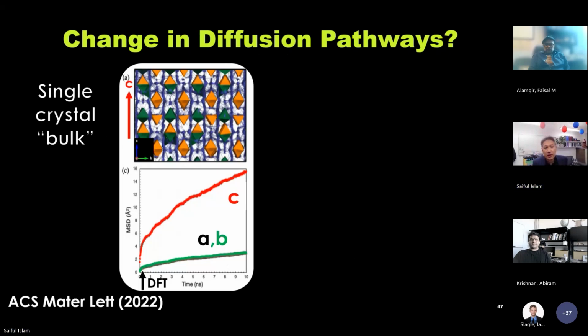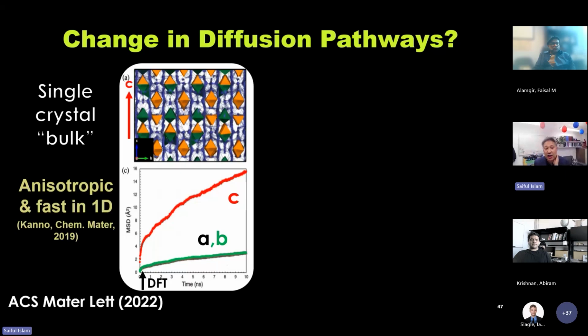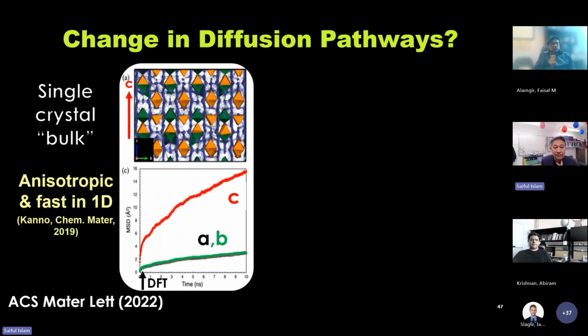I'm showing you, first of all, the bulk crystalline single crystal. On the top, I'm showing you the structure. The yellow is the PS4 and green is the GeS4 tetrahedra. The blue shows the trajectory of the lithium ions from the trajectories of the MD. You can see it's largely along the c-axis, one-dimensional. And that's confirmed by the mean square displacement below the structure. The c direction shows the greatest diffusion in red, whereas the ab in green shows minimal diffusion, i.e. highly anisotropic, fast in 1D.